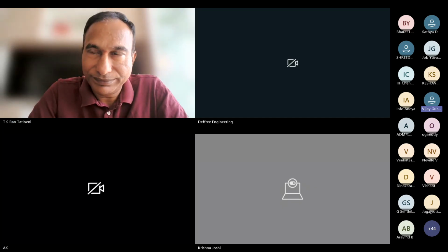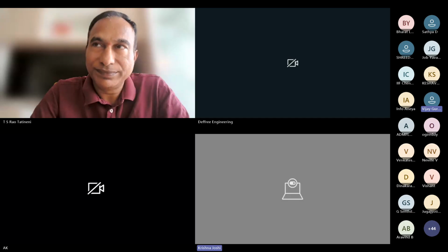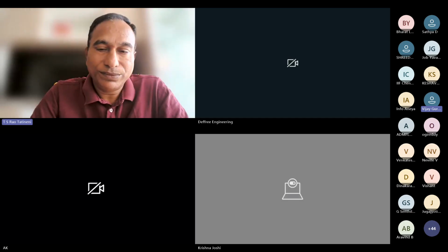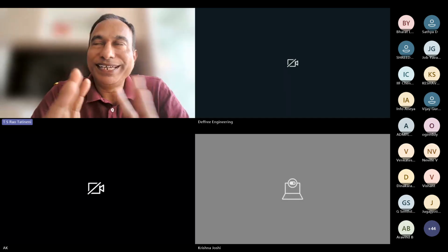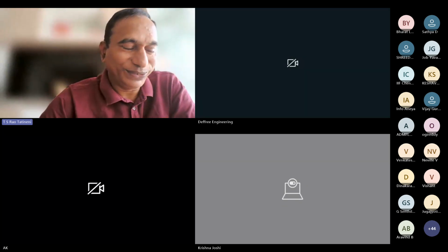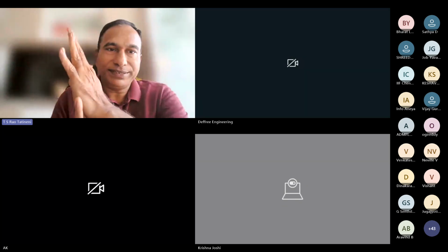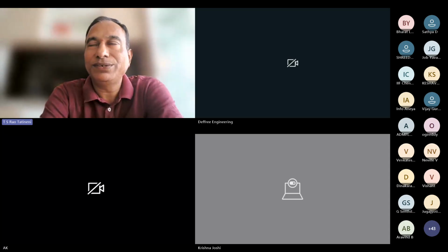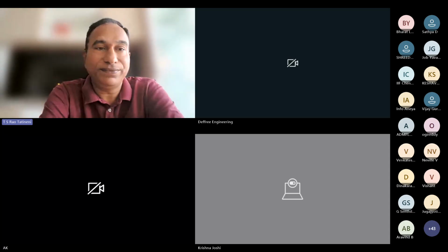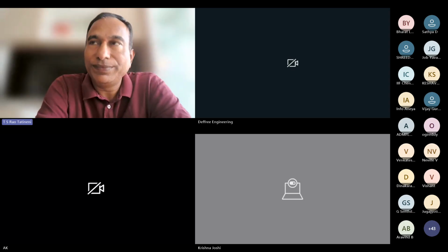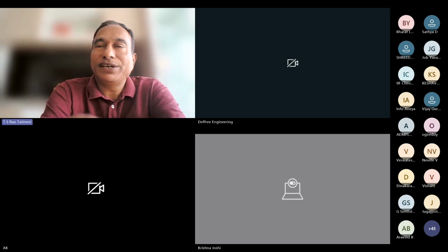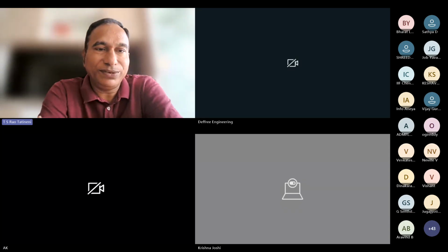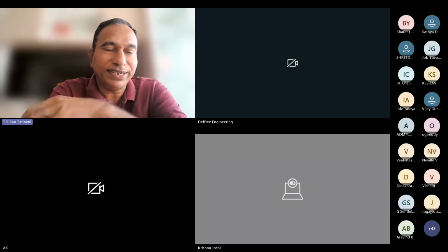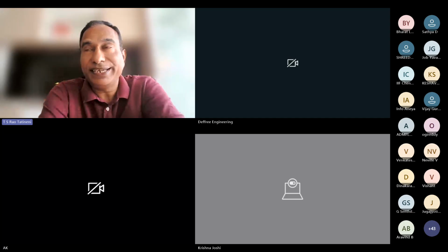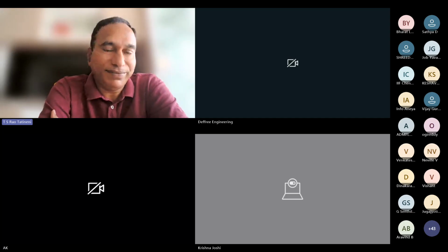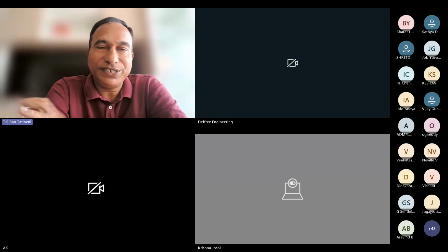Is there any telltale sign that a defect is arising out of the gating rather than the process or the sand or the metallurgy? So gating is a sarvaroga nivarani. In the foundry, it is hard to identify the root cause for the defect, but gating will help to mitigate the defects which are caused by the process. Like, suppose we take a scab, it is not directly related to the gating, but however, the gating can help eliminate the scab defect. Similarly, the metallurgical defects.